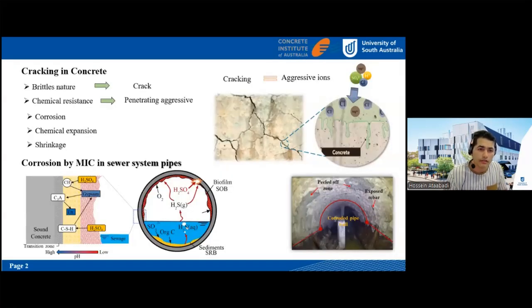However, concrete has a brittle nature, so this material is prone to cracking. Once a crack happens, it usually allows aggressive ions to penetrate inside the concrete structure. And because the chemical resistance of concrete is low, these penetrated aggressive substances or ions can cause corrosion, chemical expansion, and even shrinkage of the concrete.